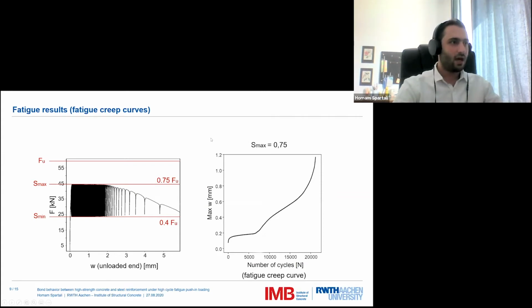Before I introduce the cyclic tests, I would like to go quickly over the idea of fatigue creep curves, in case someone is watching without a fatigue background. So we see this figure that represents the load displacement curve in one of our fatigue experiments. Fu is the maximum value reached by the corresponding monotonic test. In this case, we use a maximum load level of 75% of Fu and a minimum of 40% of Fu. If we take the slip at each one of these peaks, we can plot these with the corresponding number of cycles at each one of these to obtain the fatigue creep curve.